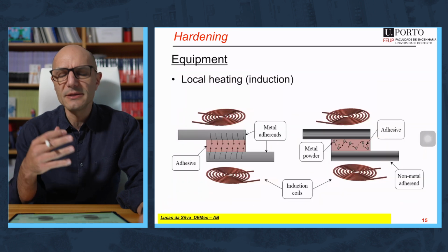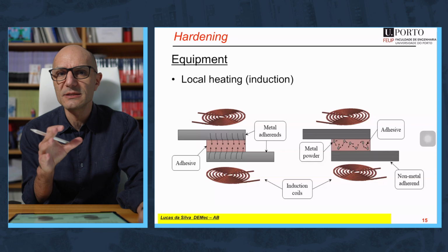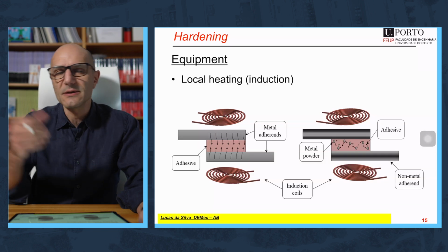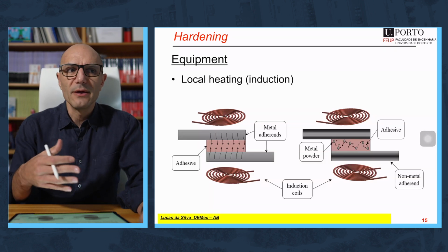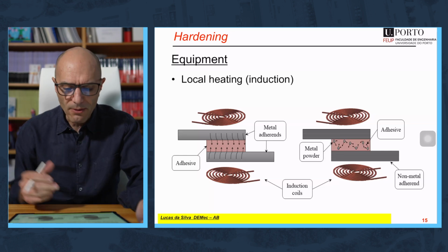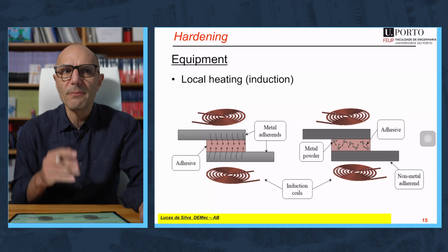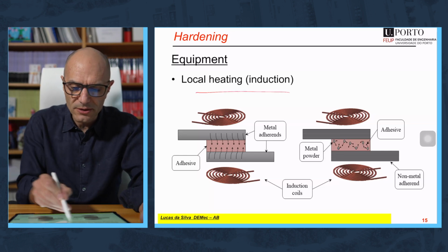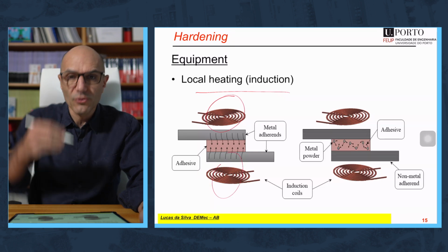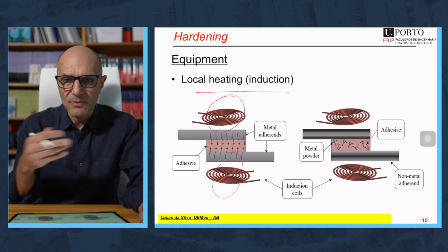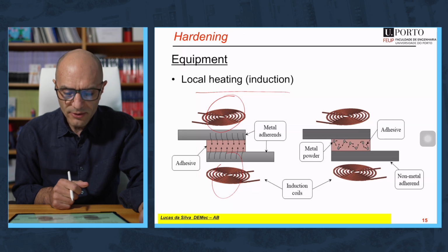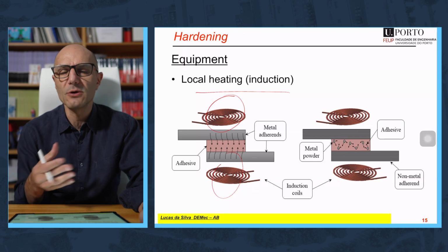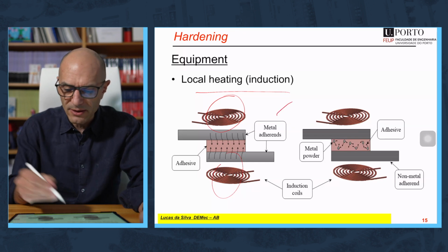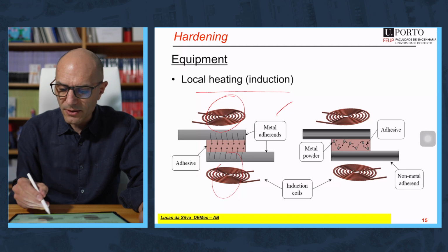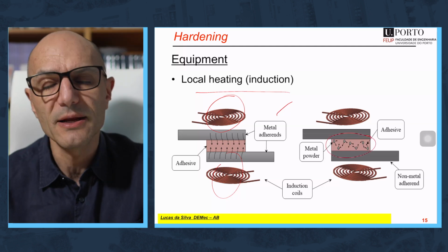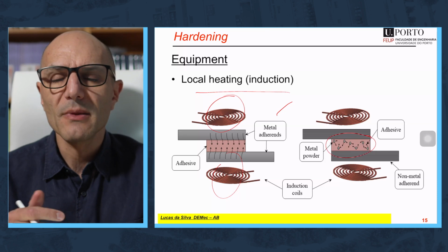Sometimes you are interested in heating only a local place of the joint. This makes sense more in industrial applications with big components. There are several ways to apply a local heating. You can use induction heating, where you use coils to induce a current in the joint, and then by Joule effect you have a heating of the joint, but this works only with conductive substrates like metal. In case of composite it's harder, but you can load the adhesive with metallic particles and then it works.